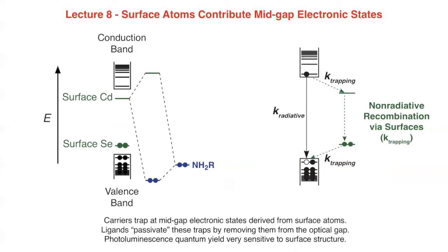And that connection leads to an orbital splitting, just like in any other orbital interaction. And so the acidic cadmium ion stabilizes the electron pair on the amine ligand, and the basic donor amine destabilizes the surface cadmium. So in other words, after the amine is bound to that surface cadmium, it's much harder to put another electron pair there.